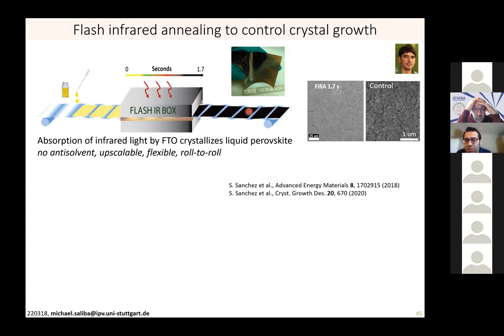This method, rapid thermal annealing, is of course known from established technologies like silicon and so forth. But instead of using 1 hour for the annealing time, it can be used here to control the crystallization. And you see here how the grains change dramatically. So this is to tell you that the heating protocol matters. You may write down all the inks that there are in the world, but crystallizing them in a systematic way is also very hard. And this could be a tool to form or to control the crystallization in the future.